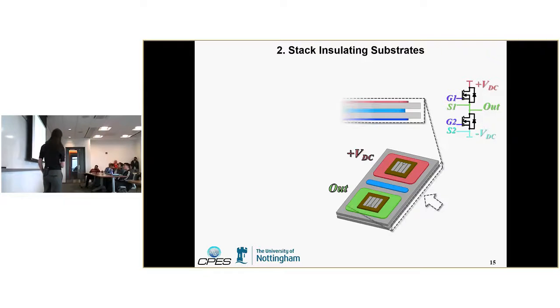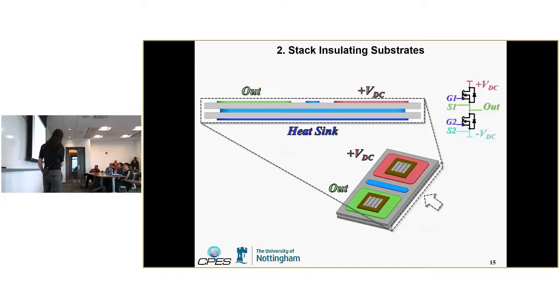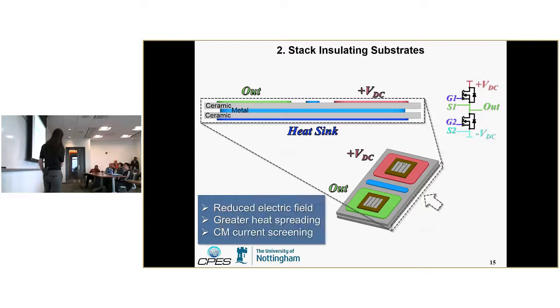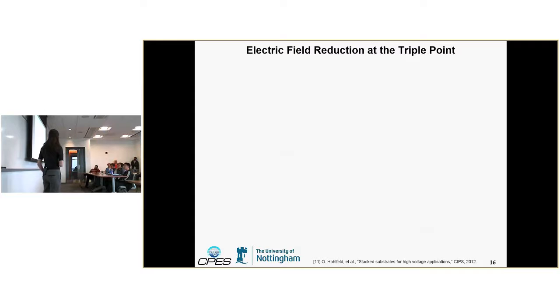We're also stacking these substrates. This is what that looks like. We've got two metal ceramic metal substrates, one on top of the other. There are three main reasons for this. The first is to reduce the peak electric field. Second is to increase heat spreading, and third is to create a common mode screening effect. I'll go into all of these now.